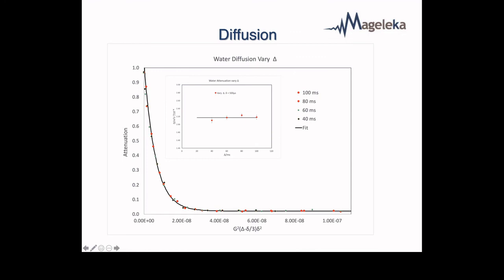Now, in bulk water, the diffusion coefficient is independent of time. Eventually, it'll hit the side of the tube and bounce back again. But we're looking at distance scales between 100 nanometers and about 100 microns. That's how far we can follow the trajectory of a molecule. And you can see for my water sample that it's independent, as you'd expect.